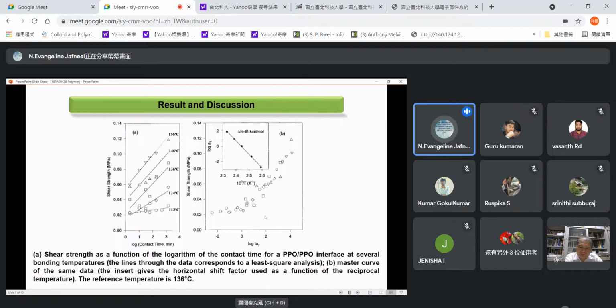Next, the shear strength developed at the PPO interface was given. The first graph shows the log contact time versus shear strength. Here we could see a gradual increase in shear strength when the temperature is increased, and the 136 degrees Celsius master curve was chosen for the reference temperature, and the corresponding Arrhenius plot is also given. With the help of the Arrhenius equation, the enthalpy was calculated as 81 kilocalories per mole.